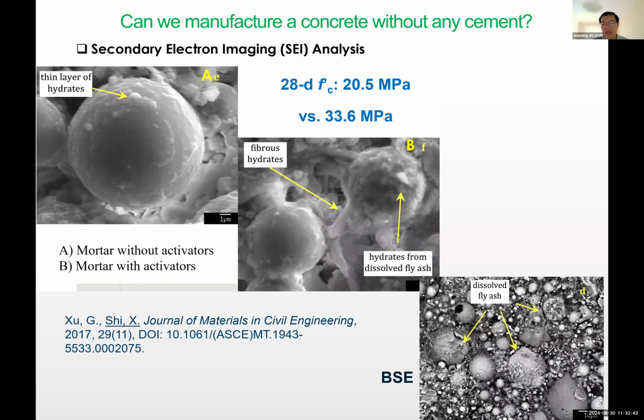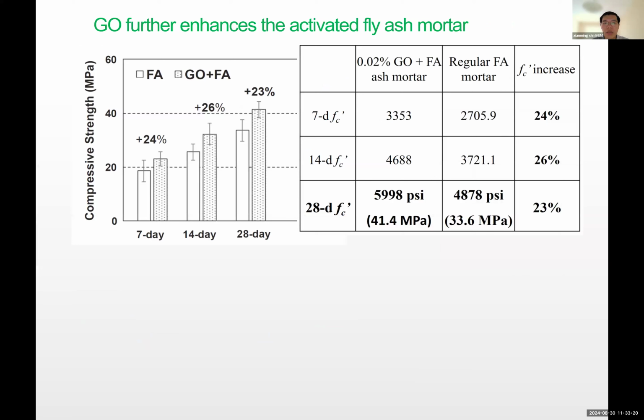So that's all good. And then a backscatter electron microscope reveals even more information, because in addition to morphology, the brighter constituents indicate a heavier element. So this gives not just morphology, but also some hint of the chemistry. Now, with a little bit of activation, we can get to 34 megapascals-ish, which is roughly 4,900 psi, but we want to go further. So by adding 0.02% graphene oxide by weight of ash, we can increase another, roughly speaking, 25%. So you can see here these improvements from the trace amount of graphene oxide in this activated fly ash paste, at 7 days, 14 days, 28 days. So now we're reaching approximately 6,000 psi at 28 days.